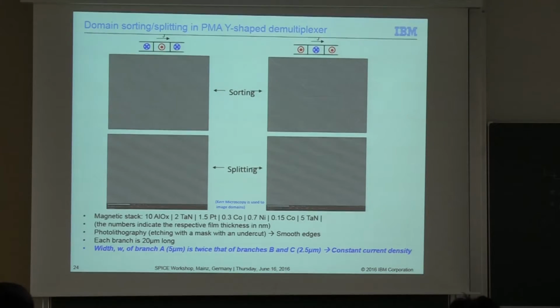And we can also do similar things where we move them by using spin orbit torques. And these are moved by using currents. And in this system, we have chiral domain walls because we have this asymmetric exchange interaction, namely the Dzyaloshinskii-Moriya exchange interaction, or the DMI. And this locks the chirality of the domain walls. So you have Néel domain walls in these systems, and the up-down domain walls have a set chirality, a set polarity as well.